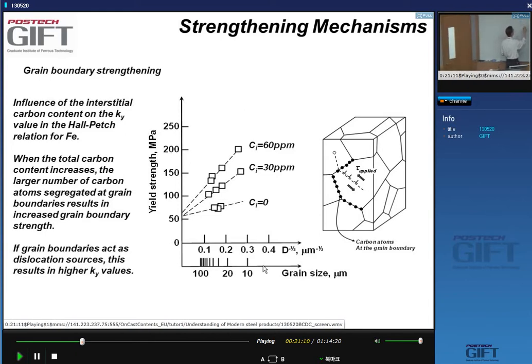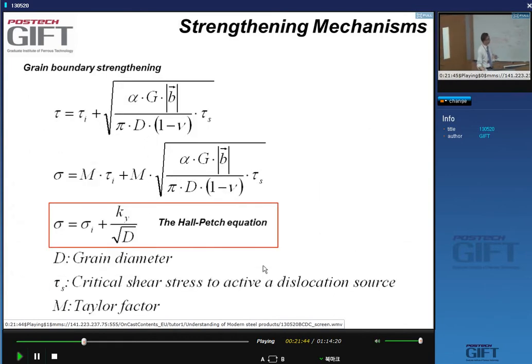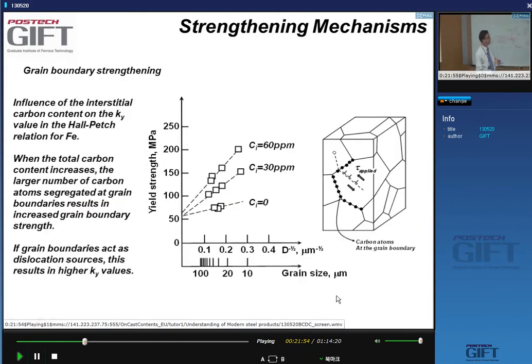So here you have 1 over the square root of the grain size, and this is what the Hall-Petch equation predicts. It's very interesting because this would be the yield strength as a function of the grain size. This point here is the yield strength for an infinite grain size, for a sample without grain boundaries. Now, according to this theory, the only parameter is the stress that's needed to activate a dislocation source.